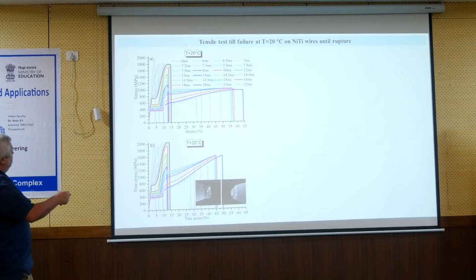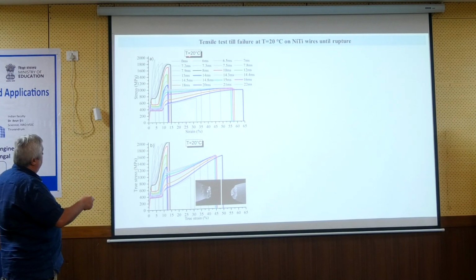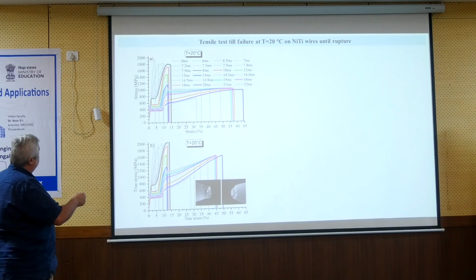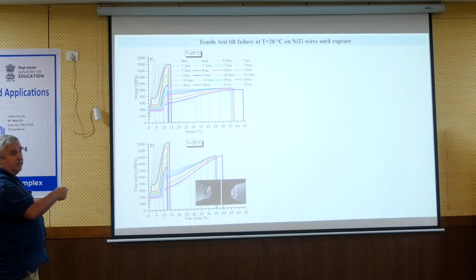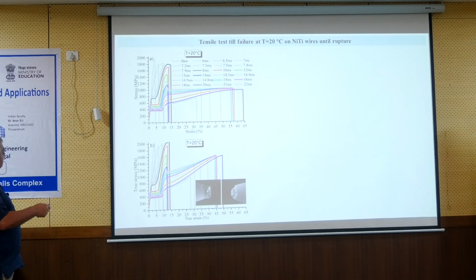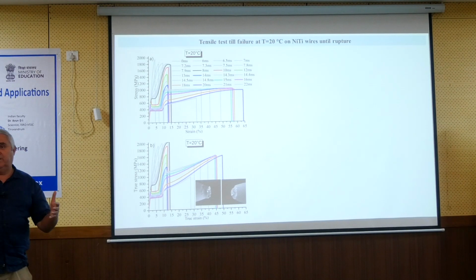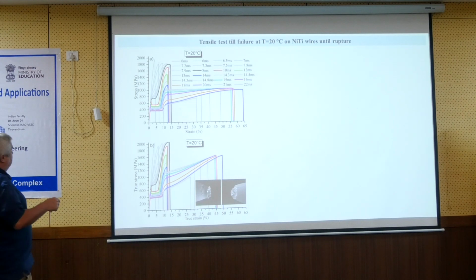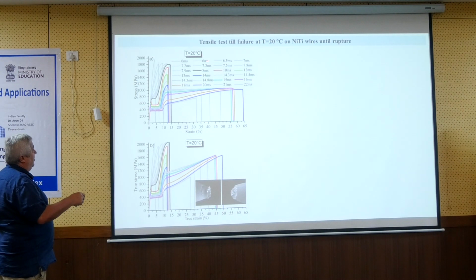So this is one at room temperature, with wires of different microstructure. The hard wire is elastic and breaks at about 2 gigapascal, as I already said. If you continue and the grain size becomes bigger and bigger, you will obtain such a pattern. The most interesting wires are here, about 10 or 12 milliseconds, which have a high yield stress for plasticity, but they all fracture around 12 to 13. So if you buy a nitinol wire somewhere, it will fracture around here. There will be no chance for you to deform it to 60%.